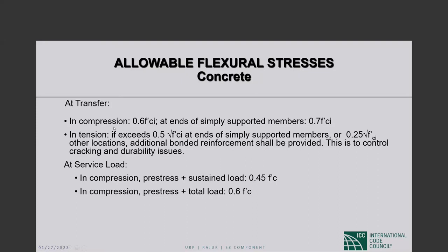So in compression, limit is 0.6 F prime CI anywhere. So if you have a compressive stress, this is the limit. And as I mentioned, F prime CI is the initial concrete strength. We collect cylinders at the initial stage. Actually, we collect cylinders, doesn't matter what stage, it has to be during casting. And then we test some of the cylinders initially, depending on when the pre-stress is released. If it's steam curing, we have been doing it at 2 or 3 days. And then we test the rest of the cylinders at service, which would be 28 days typically.